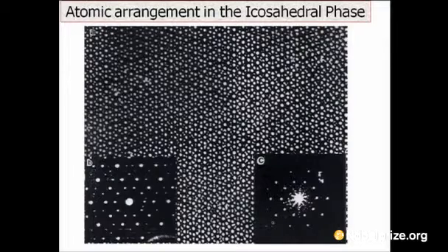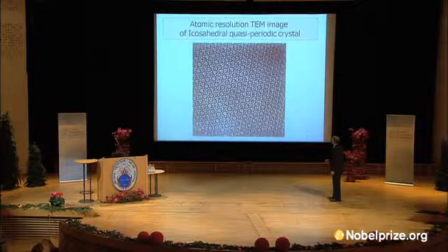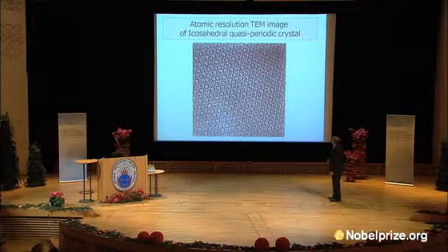But then what you can do as an experiment is the following. You can limit your field and bring it down to minimum, and still this diffraction doesn't change. It will fade away for lack of information, but it doesn't change. So it was clear by now that these are really special crystals and really something new. And this is a more modern picture of quasiperiodic material, and you can see some building blocks here. You see all these tenfold patterns which never repeat themselves in a periodic way.